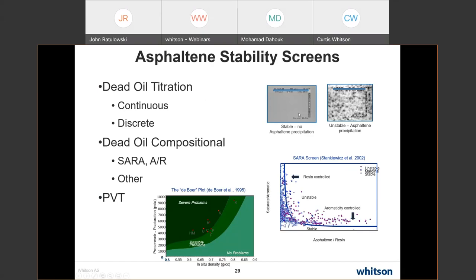So, again, there may be some image processing potential here to more standardize the actual identification of the phase boundary. So that's one type of analyses. And just to also mention that the dead oil titration is used often in the modeling as well. It gives a data point relevant to the oil and the asphaltene that can be used to help constrain thermodynamic models.